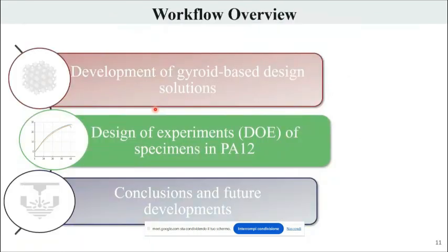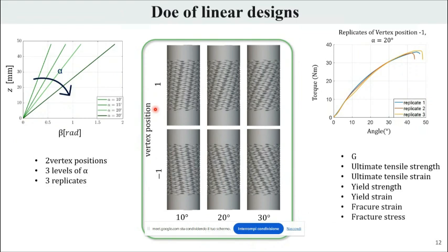We performed two different designs of the experiment. One for the linear specimens. So we defined two vertex positions. In this case, for linear specimen, vertex position can be seen as the slope of the line, and three levels of alpha, 10, 20, and 30 degrees, and 3 replicates per each specimen. And then after performing this test for torsion, we extracted the most important parameters. So yield strength, the ultimate tensile strength, and so on.